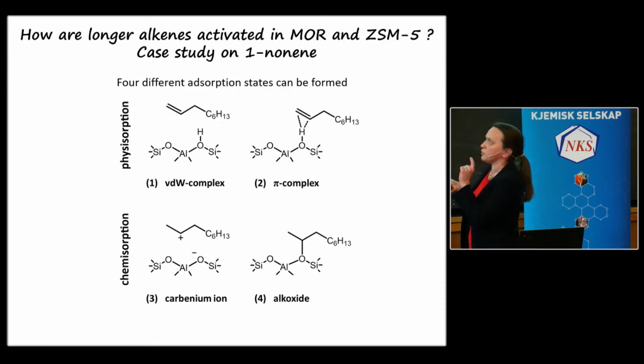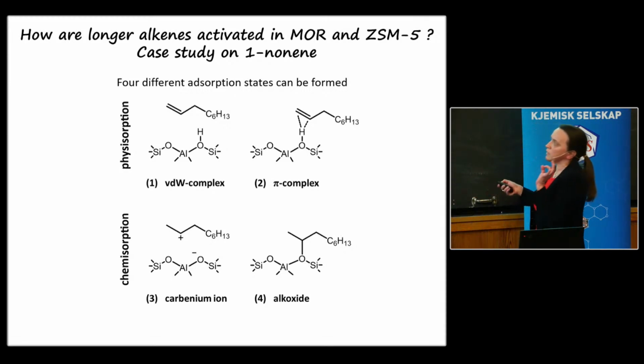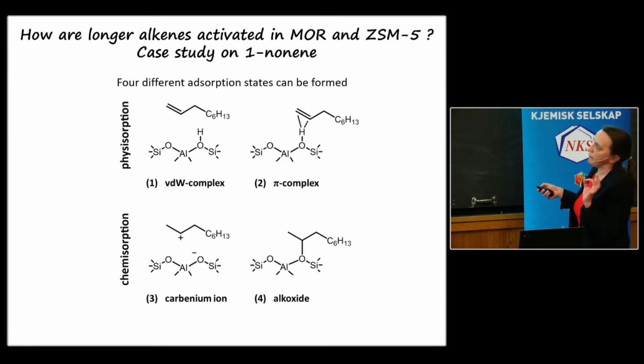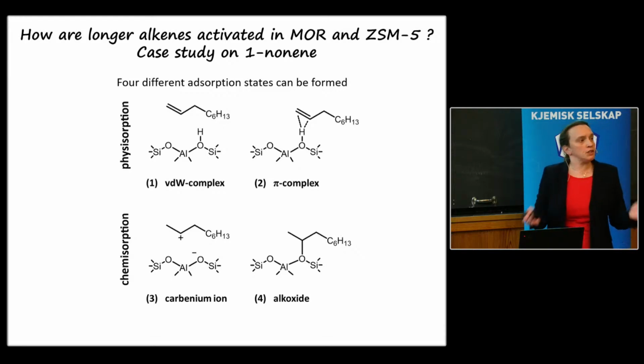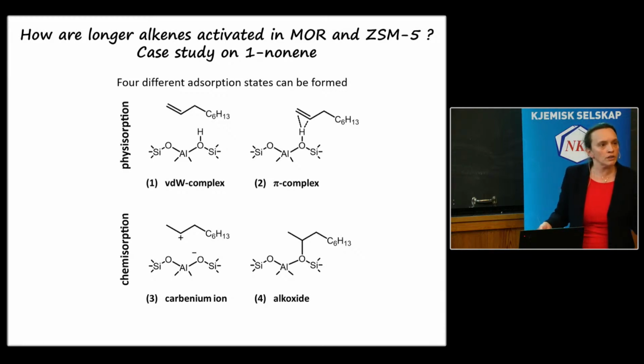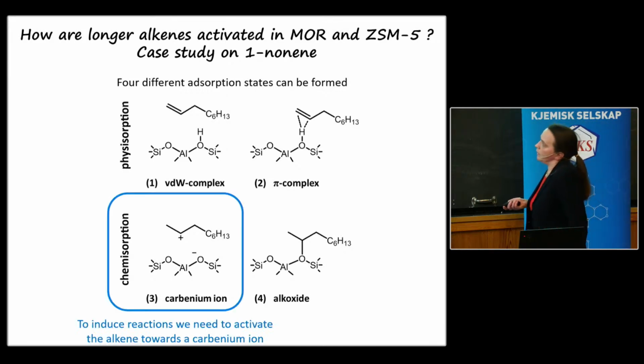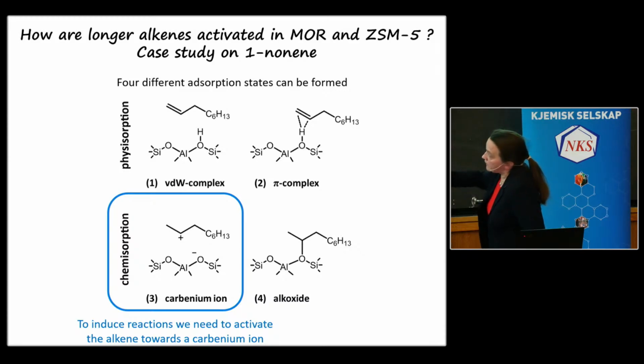If you look in the literature, many people assumed that when you do this adsorption, these species form alkoxide, where you make this bond with the zeolite. Yeah? These were simulations that were done at 0 Kelvin. No dynamics, sometimes with smaller clusters and so on. Okay. So these are the interesting species that we need to do reaction.